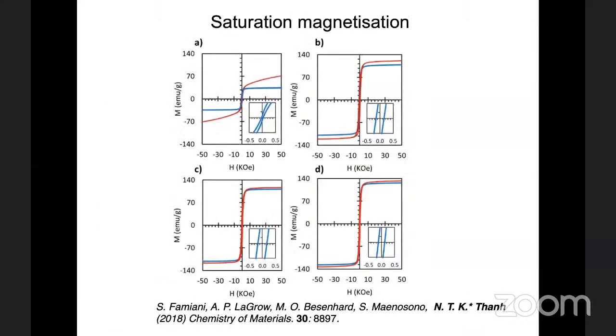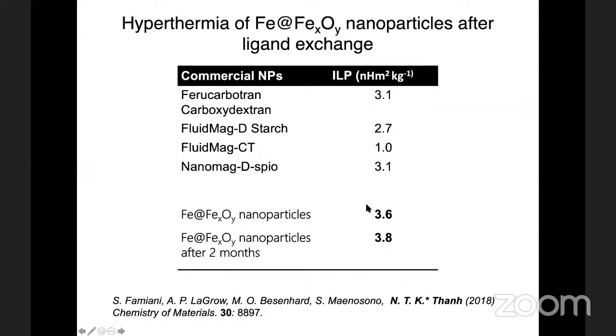We studied the saturation magnetization, and it is very high. Compared with commercially available magnetic nanoparticles, our nanoparticles have a higher heating capability, measured by the value called ILP, the intrinsic loss parameter. Basically, it means they heat better, and they are also stable for 2 months.